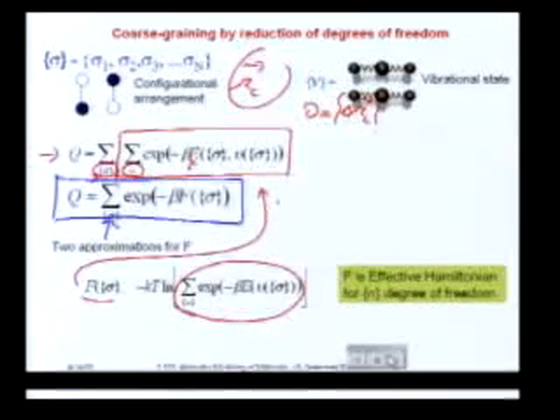So in essence, if I sum over lattice model states, I put A's and B's on different lattice positions, what this is telling you is that the quantity that's my Hamiltonian is not the energy of that state. It's the vibrational free energy of that state. So if I take that as my Hamiltonian, and then I do this partition function, I will essentially have an exact result. I will have the exact partition function of the system. Okay? And that's pretty amazing because I've really sort of separated the time scales, integrated over them separately, but I get what's essentially still an almost exact result.